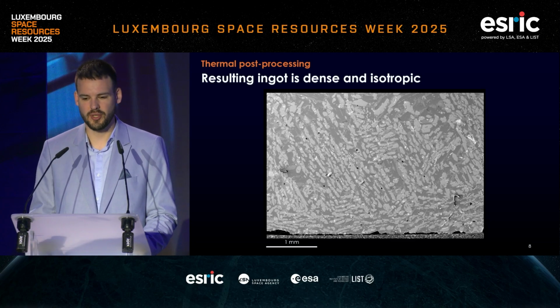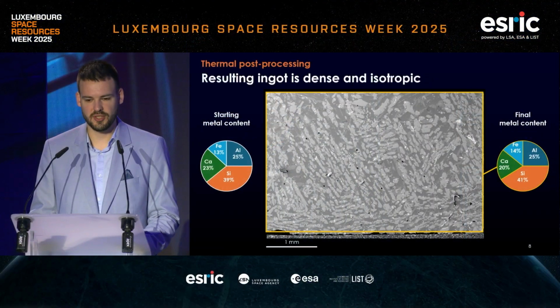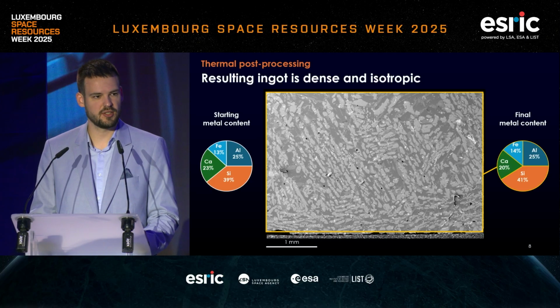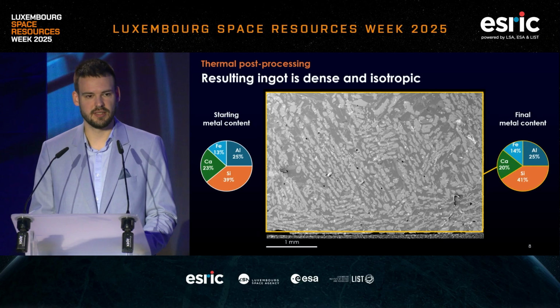This is kind of what we were looking for to get from our products out of the FFC process, but when you apply similar post-processing to actual products coming out of the FFC process, things get a bit more complicated. Here, just for the composition, again, not many changes. We get out what we put in, so we don't have many losses. We do have a slight decrease in calcium, but that's also within the measurement margins.